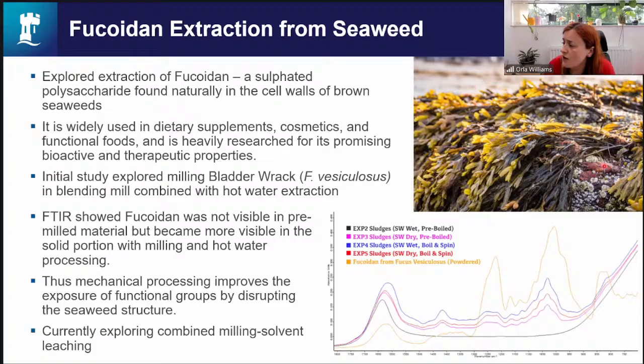This is what it looks like, and you see this a lot on the UK coast. What we did was look at blended milling combined with hot water extraction. Now, we used FTIR to show that fucoidan was not visible in the pre-milled material, but became more visible in the solid portion with milling and hot water processing.